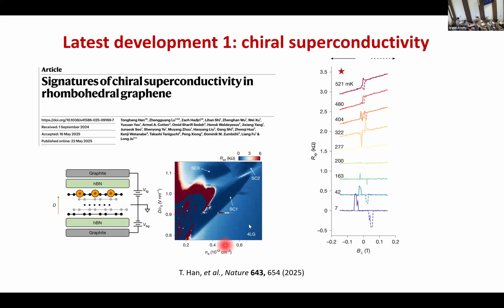In a recent paper by an MIT group, they observe superconductivity when you apply some displacement field. And there are several superconducting states. They call these SC1, SC2, SC3. Within this SC1 state, around this point, when they measure the Hall resistance by sweeping the field, you can see that it shows some hysteresis. And when you cool down, you still see some kind of jumps around this coercive field when it's already in the superconducting state. So this is why the system becomes quite interesting.